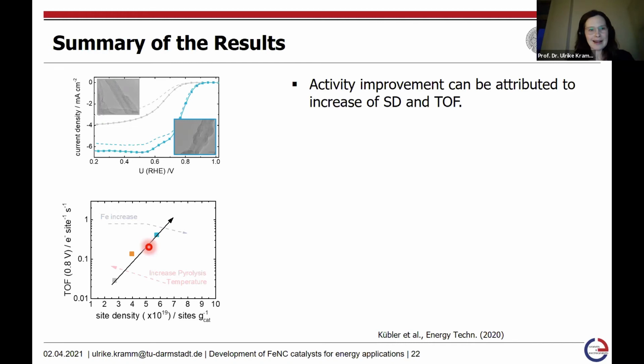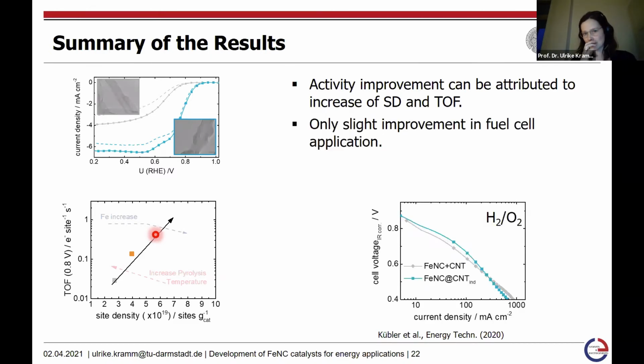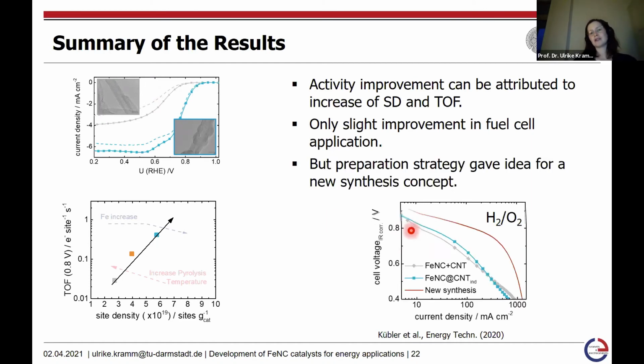What I have not told you so far is that, unfortunately, for this preparation it's not really easy to scale up the site density. The site density for this system, even after this improvement, is still much lower in comparison to other FeNC preparation strategies. Also, when we went to fuel cell application, this improvement, as we were able to see in the RDE experiment, does not really show up as nicely during the fuel cell testing. But fortunately, this was a good starting point for the development of a new preparation strategy.